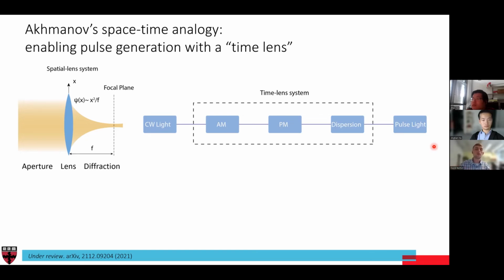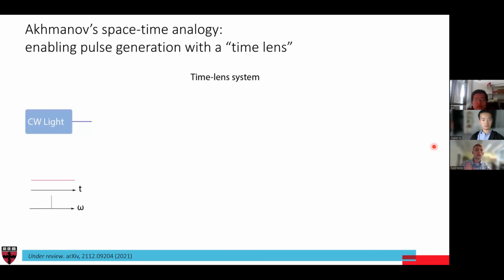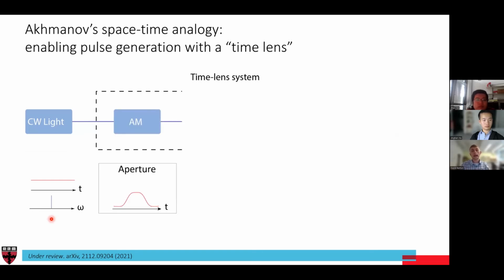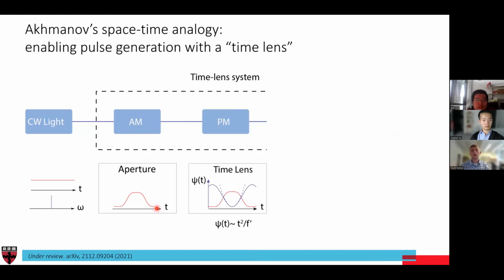And so to show that maybe a little bit more explicitly, if we send in light that has one frequency component, one very nice laser coming out of a laser diode, if we send that through an amplitude modulator that changes the allowed amplitude with time, we actually end up carving out the same aperture function that a lens might have. Then by sending it through a phase modulator, we can give it a parabolic phase, it maps almost directly to the sort of phase profile that a lens will actually give you.